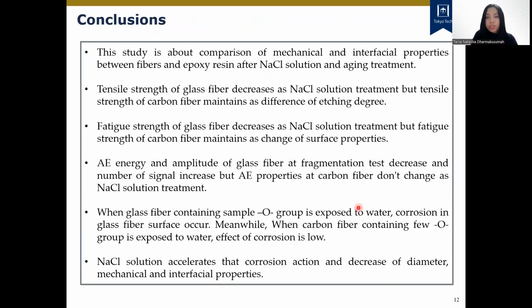So the conclusions are: the tensile strength of glass fiber will decrease with NaCl solution treatment, but the carbon fiber is maintained. And the fatigue strength also has a similar result to the tensile strength. And also we can conclude that the NaCl solution treatment will accelerate the corrosion action and decrease the diameter of the fiber itself, and also decrease the mechanical and interfacial properties.